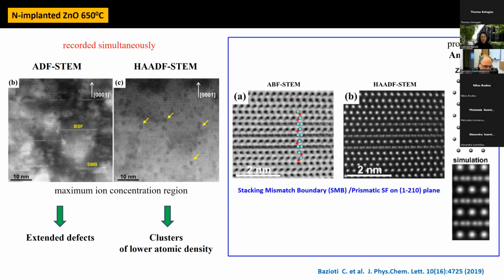The first step was to do structural analysis in order to understand what types of extended defects we had. Again, here you can see one example of high-resolution images along these defects. You can see again how useful is the complementary information that we gain from different detectors. In HAADF, we can see the atomic columns only of heavy elements, of zinc in our case, while in annular bright field, we can visualize both zinc and oxygen. So you can see that in aberration-corrected microscopes, we can easily resolve the zinc-oxygen dumbbell, and this helps us to follow the stacking sequence and to see easily what violations we have of the stacking sequence. And also imaging in that mode helps a lot to see if we have changes of polarity in the case of polar materials.